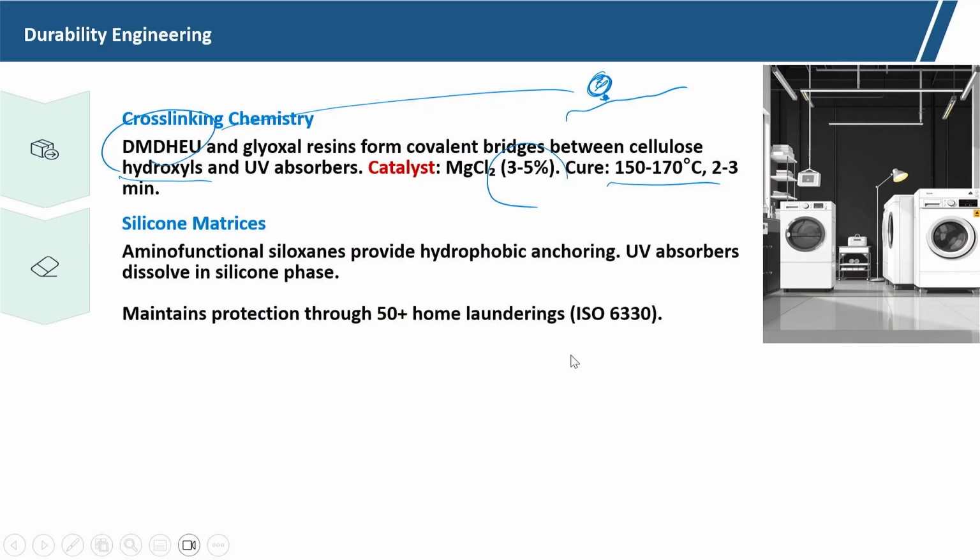And another method we can use to enhance the durability is silicone matrices. Amino functional siloxane provides hydrophobic anchoring, and the UV absorbers dissolve in the silicone phase.